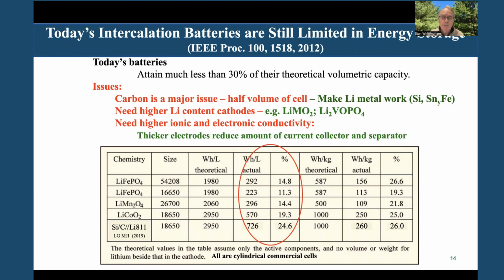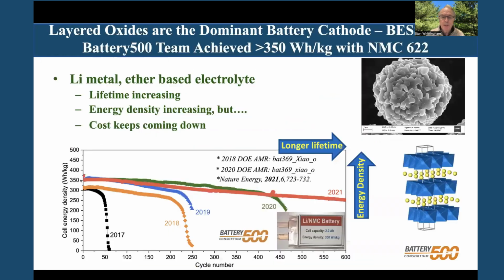And we have a major program with the Department of Energy here to increase that to 50%. To do that, we've got to get most of the carbon out. We've got to get more lithium in, and we need materials with higher ionic and electronic conductivities so we can make the electrodes thicker. So what we're doing in this DOE project, this is called Battery 500, is to increase that energy density from 250 to 500 watt-hours per kilogram.